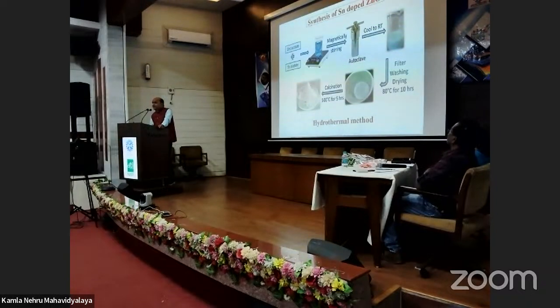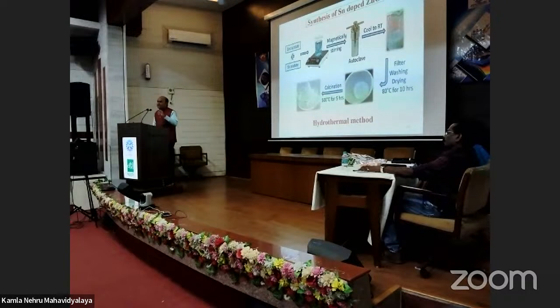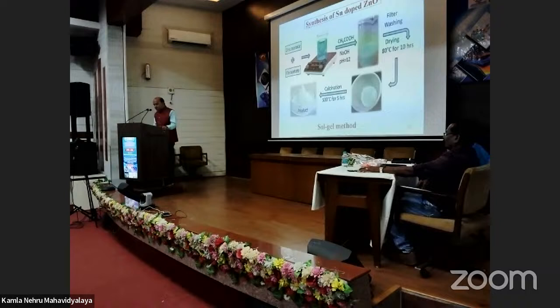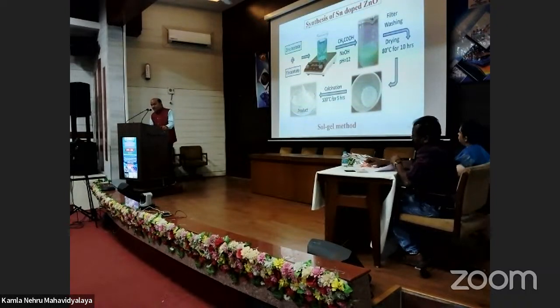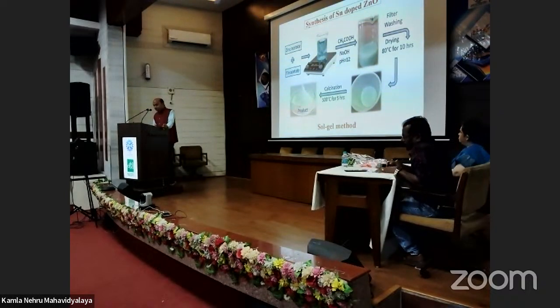The second method we have adopted is the hydrothermal method. The same process, but instead of direct co-precipitation, we put that entire solution into the autoclave, because temperature control as well as pressure control is possible. In co-precipitation, temperature control or pressure control is not possible; it is atmospheric pressure. So one is the hydrothermal method, the second one is the sol-gel method, and upon comparing all these, we found that the hydrothermal method is the best method for the tin doped zinc oxide.